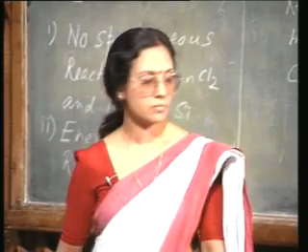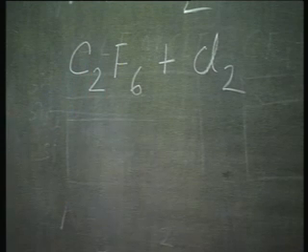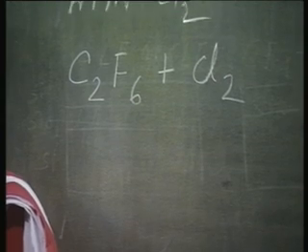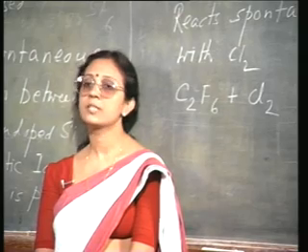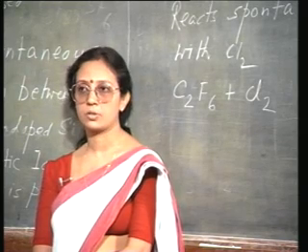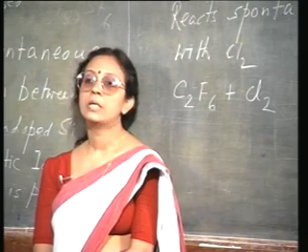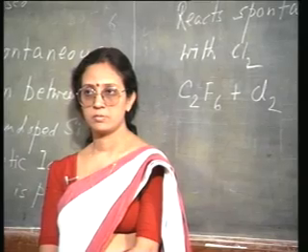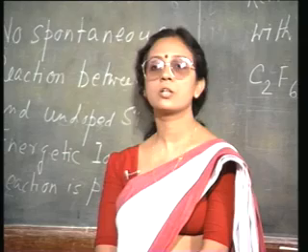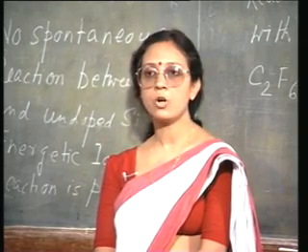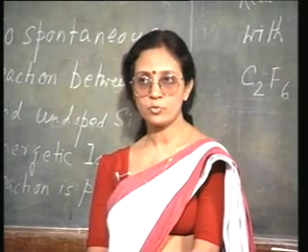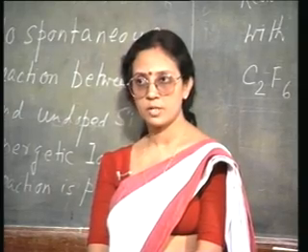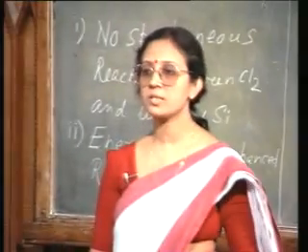And particularly this is a very interesting reaction. See, I am using C2F6 and chlorine. Now, silicon dioxide does not get etched by chlorine. Silicon dioxide does not react with chlorine. But you know, your native silicon, the basic silicon wafer, will always have some native oxide present on that. So, if you try to etch it simply using a chlorine plasma, etching may not be very fruitful because you have some traces of oxide present on the surface. That oxide is not getting etched, therefore etching cannot progress. So, even there this feed gas is going to help, C2F6 plus chlorine.